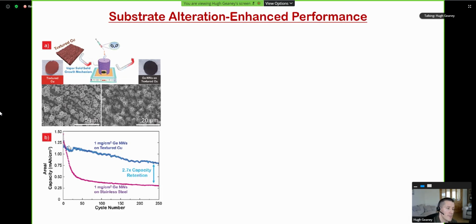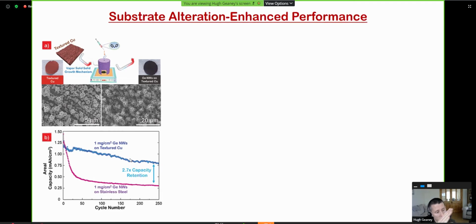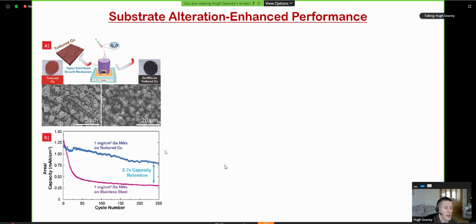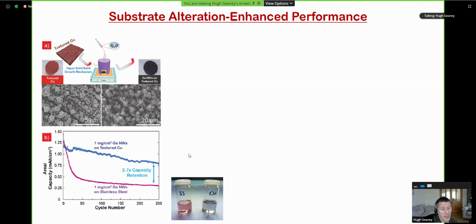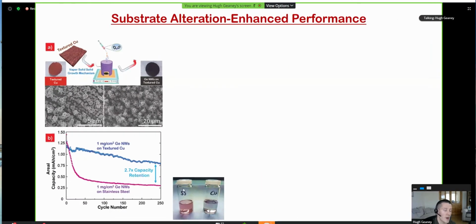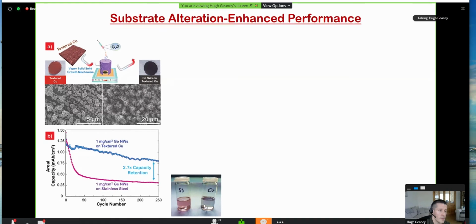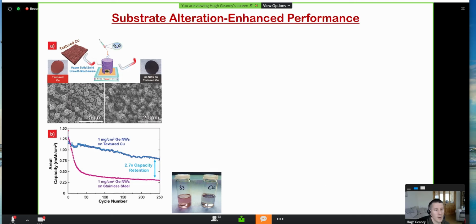So when we compared these copper-based current collector nanowires to the ones that were grown on stainless steel, we had a dramatic improvement in terms of the capacity retention. And you can see that this is from starting out at the same areal capacity here. So at the end of 250 cycles, the capacity retention was about 2.7 times better on the copper current collector than it was on the stainless steel. One of the main reasons explaining this was that we physically couldn't remove the nanowires from the current collector prior to the testing within the battery. So if we took our germanium on stainless steel and sonicated the nanowires, they would come off, whereas on the copper, they were deeply embedded in the current collector and very well attached and wouldn't come off.